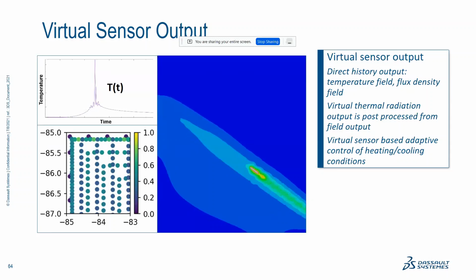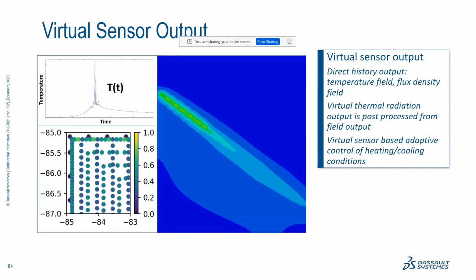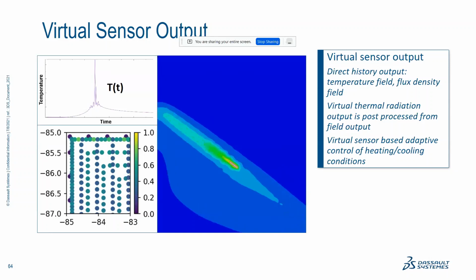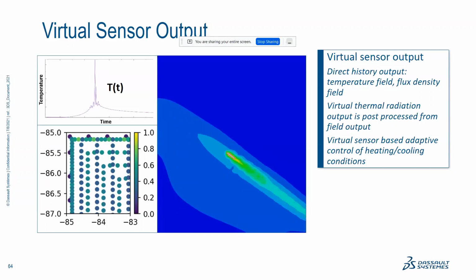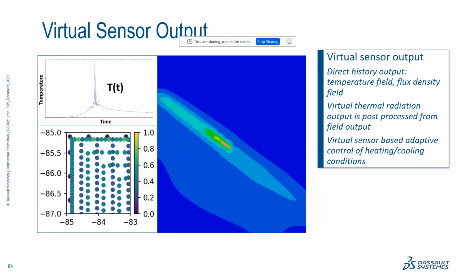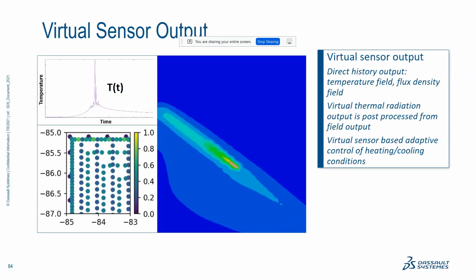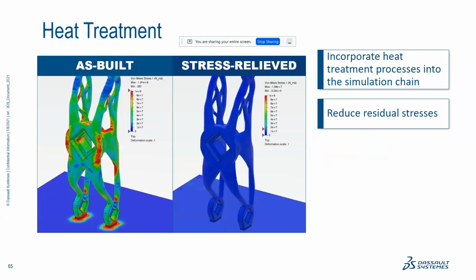So as you can see in the graph, so we can activate the historical output. So over time, what is the temperature? And then we can find out at what point is the heat being applied at a certain location, and what is the time it takes to dissipate the heat to a steady state. And those kind of details give insight into, say, any hotspot regions or any weak regions, which we can eventually correlate with the part validation. So then, as a result, based on this, we can change our scan strategy suitably.